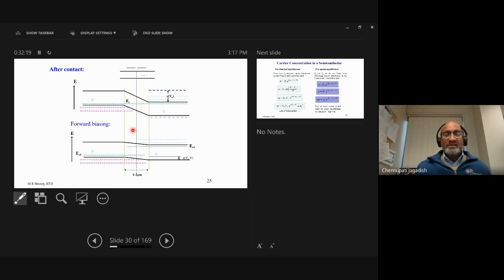Whenever you forward bias these, the band bending changes, and you end up creating so-called quasi-Fermi levels. Instead of having a single Fermi level covering both n and p type, you end up with a quasi-Fermi level for the holes and a quasi-Fermi level for electrons. That means you have large concentrations of electrons here and large concentrations of holes here, and they recombine, generating light, particularly if you're using direct band gap semiconductors.